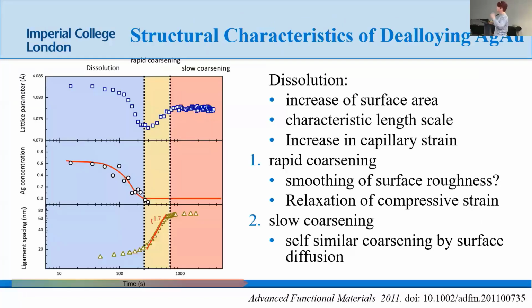All right, so then we can put those things together and correlate the time. And you see actually this middle graph, the amount of silver left, we've done that two ways, both from ICP of the solution and some in-situ X-ray experiments. You see the silver starts to dissolve and then it goes to near zero, never goes to exactly zero because there's always the odd silver atom that's just trapped right in a cluster of gold. But as the silver is almost all gone, that's when you see the ligament spacing, this huge rapid coarsening kinetics, and that's when you see that you've reached your maximum strain. So these three parameters are all coupled in the system.